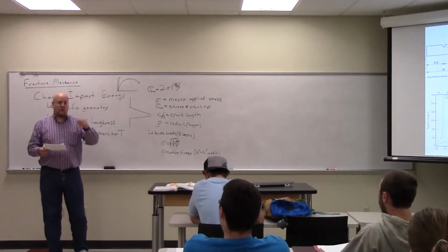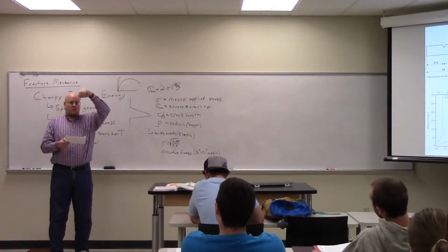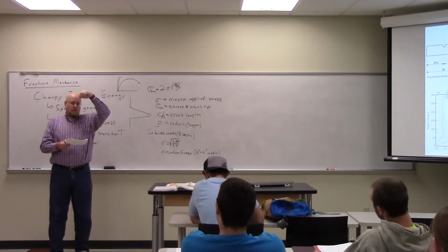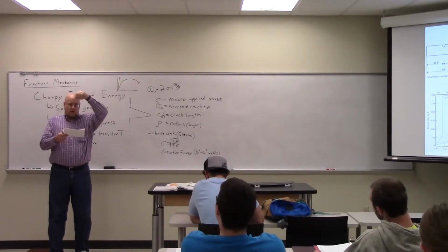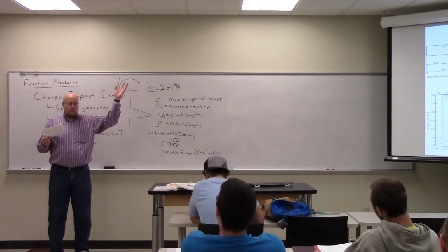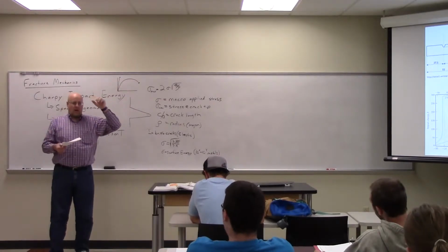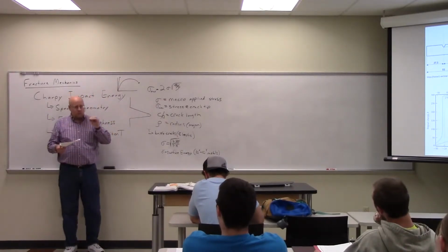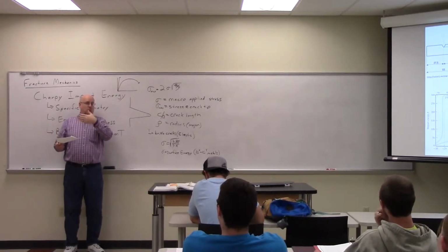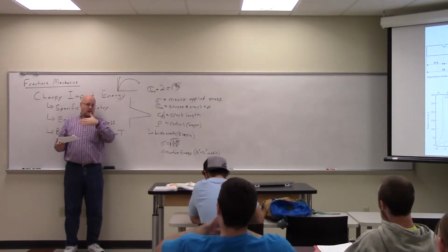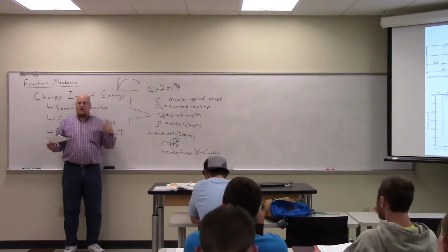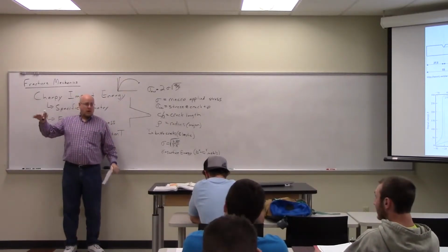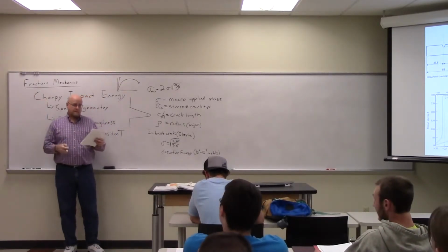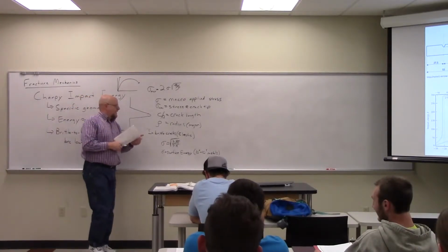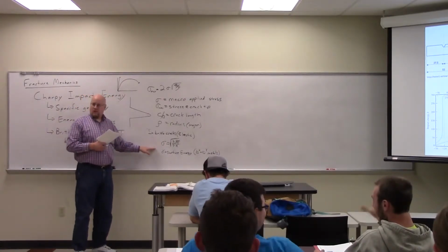So that's why it's very difficult to control, to take a piece of glass and get the crack to grow partway through it. If I have a crack in the glass, I pull on it, boom, it pops all the way through. It's catastrophic. Glass doesn't generally fail in little bits and pieces. Now, in your windshield it does, because remember we talked about the fact there's another layer there gluing together, so it's getting support. But if I take this window, once the crack goes, it goes everywhere. Okay, so that's for an elastic crack.